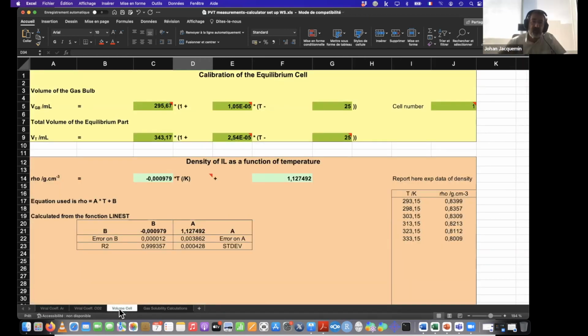And if we have isochoric techniques, we need, of course, to first get the gas bulb volume, which could be calibrated in different ways, but we decided to calibrate separately using water. And of course, we need to take into account that the calibration must be done at different temperatures because we have a stopcock, we have a valve, which may be a different material. And in order to calculate the dilatation coefficient, to correct the volume change due to the increase of temperature, the coefficient is here. And here is the expansion coefficient for glass, for example. And then we did the same PVT measurements to calibrate the glass cell, thanks to a very well-known volume, and to determine the total volume.